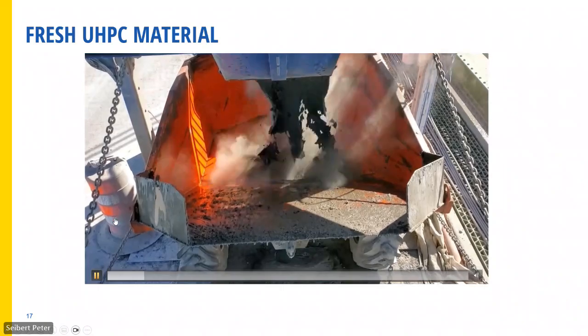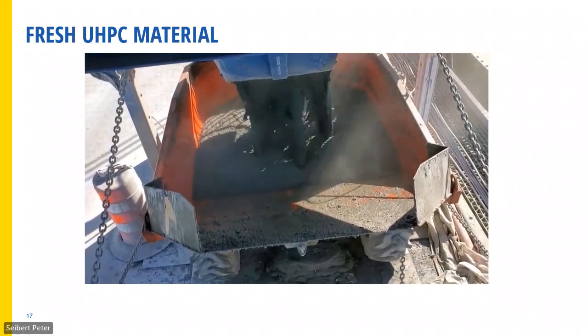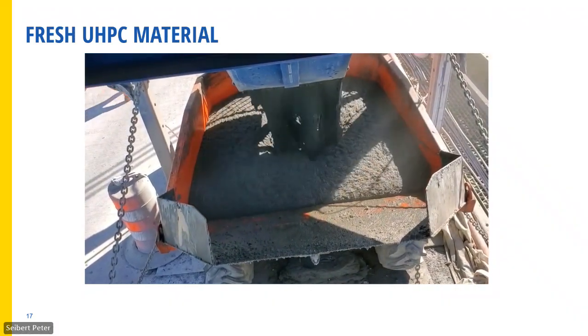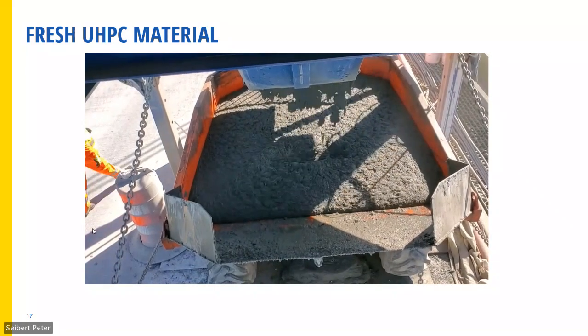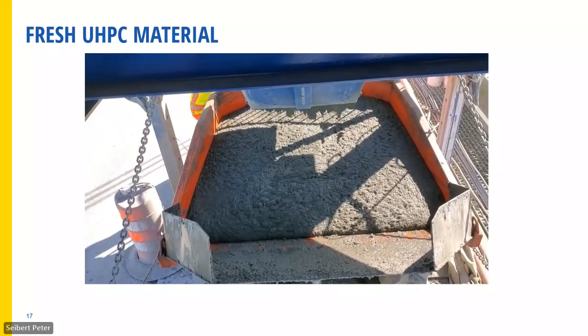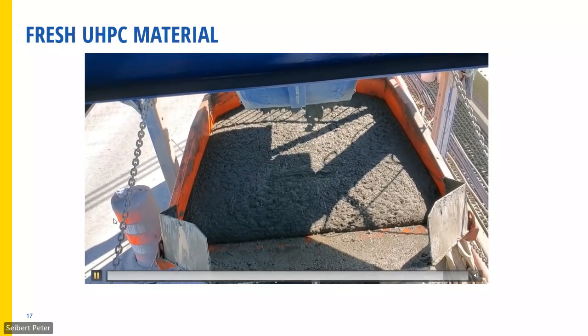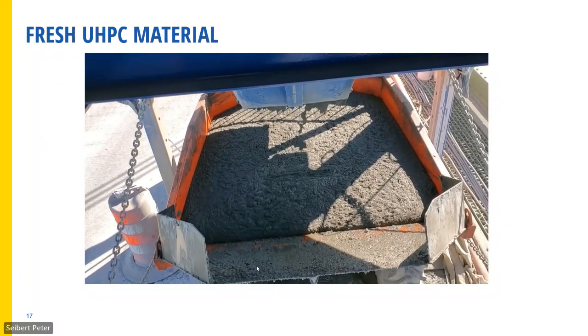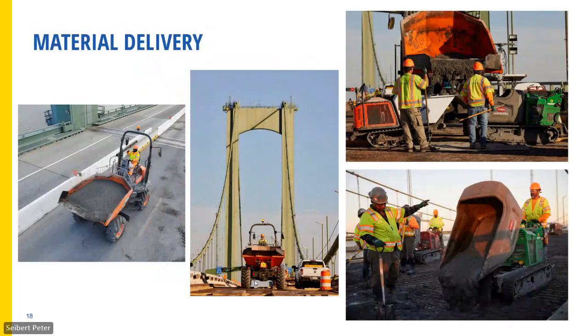So each batch would take about 25 minutes. And you could see here a nice fresh batch of UHPC coming out. We batched 5 cubic yards at a time, and we had 2 of those batch plants set up on the project. We were pushing volumes of 120, 125 yards in a shift to go from one joint to the next joint and do a full overlay joint to joint. So we transported the UHPC from the batch plants in these big dumpers, we call them. They proved to be a little too large to dump right in front of the paver, so we transferred the material from the dumper into Georgia buggies, and then the Georgia buggies would come up and dump just in front of the paver.